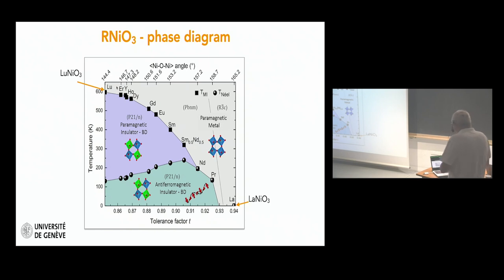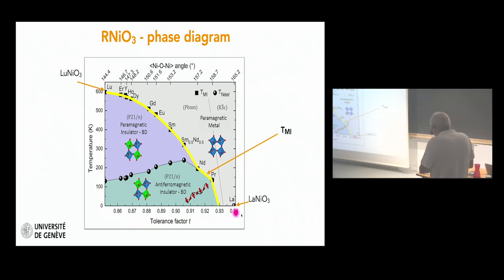And now you see an important thing. This is the metal to insulator transition as a function of the rare earths that you have in your nickelate. And you see that this metal to insulator transition temperature is related to the level of distortions of the system. So the less distorted nickelate, lanthanum nickelate, is metallic all the way down to low temperature. And now the smaller the rare earths, the larger the distortions, and the higher the metal insulator transition. And this is linked now to our tolerance factor, which is becoming smaller and smaller. The rotations are larger and larger, and the nickel-oxygen-nickel bond angle is going smaller.